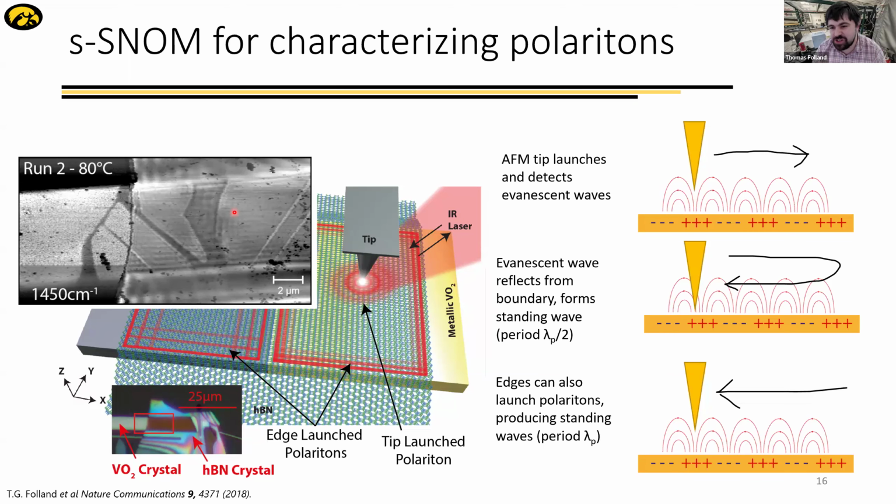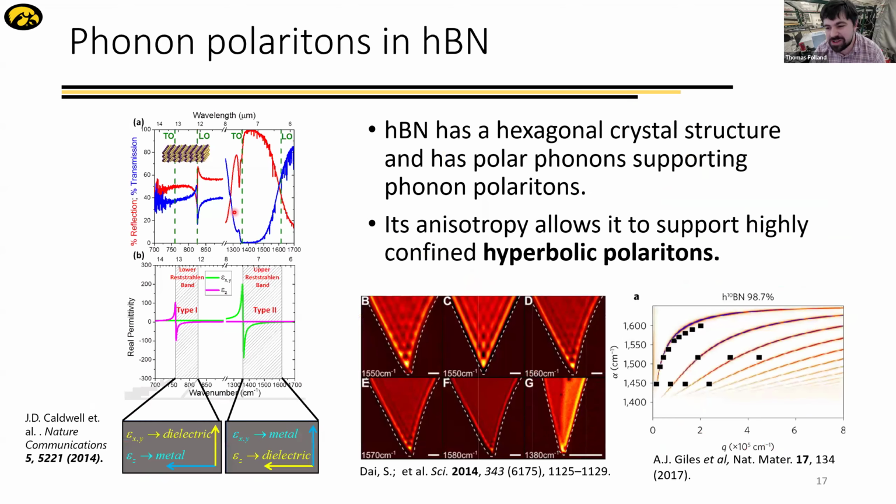I've already introduced boron nitride. Boron nitride is a really interesting material for the infrared. Obviously hexagonal boron nitride got its start in life as a gate dielectric and an encapsulant for graphene, but it turns out in the infrared it's really interesting, and that is because it has these polar optical phonons, and because the lattice is really light. Boron and nitrogen, it's one of the